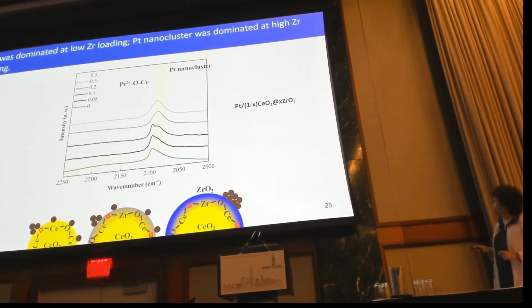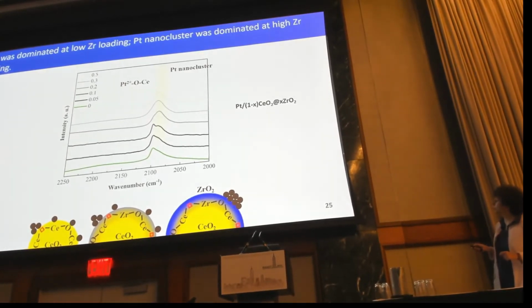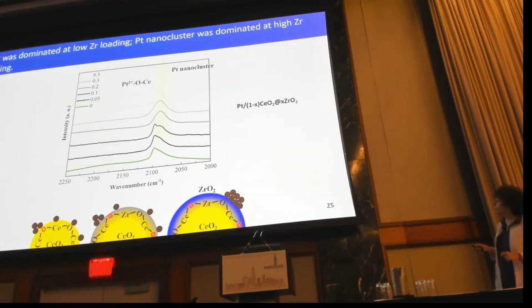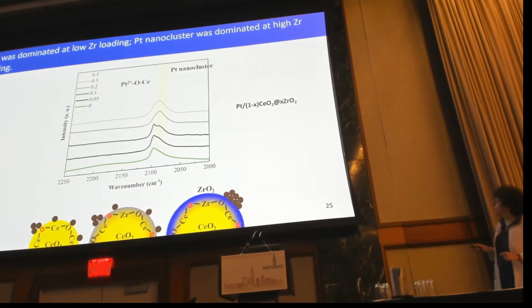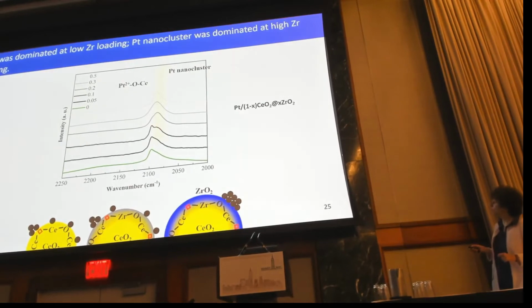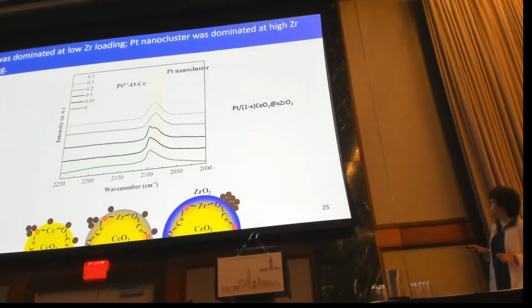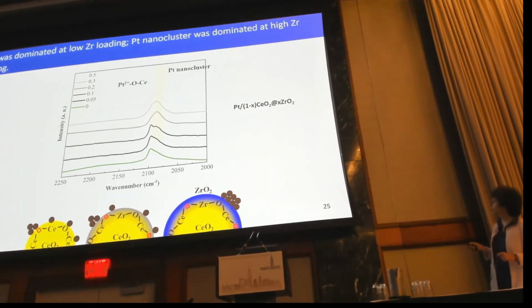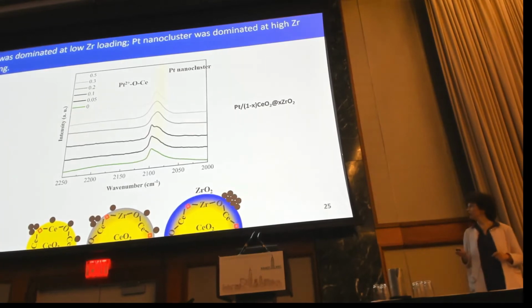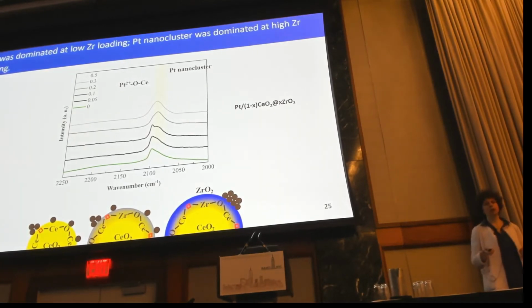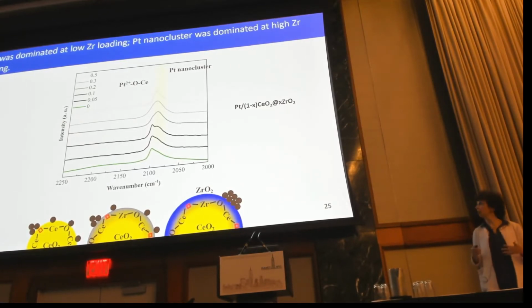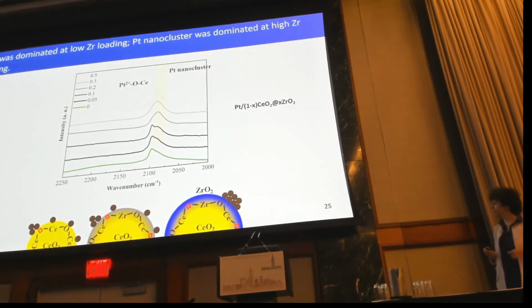But what we see is that when we increase the zirconium content, the intensity of this high wave number peak decreases, and suddenly we have the formation of this lower wave number peak that is attributed to the formation of platinum nanoclusters. Okay, so this observation agrees with the CO chemisorption experiments, showing that indeed, when we increase the zirconium content, platinum forms big platinum particles on the sample.